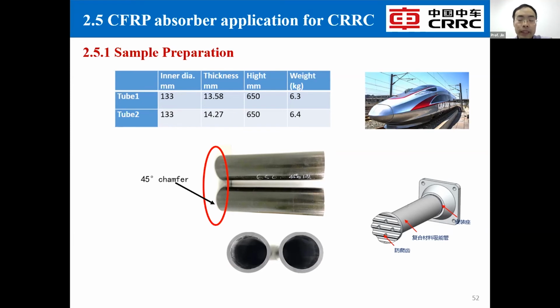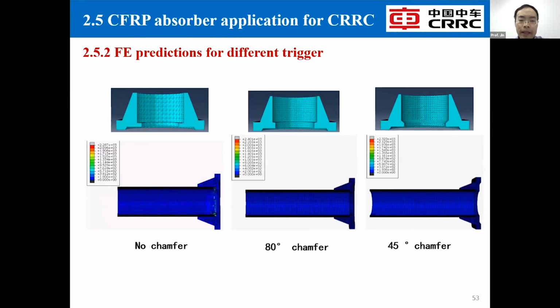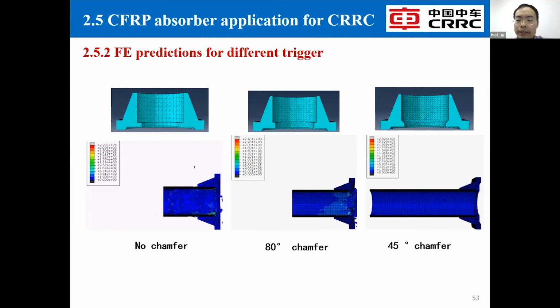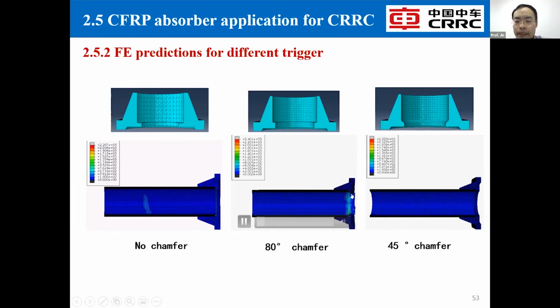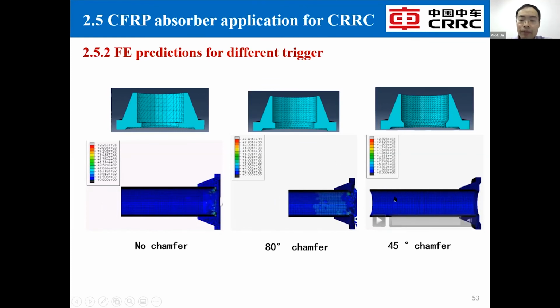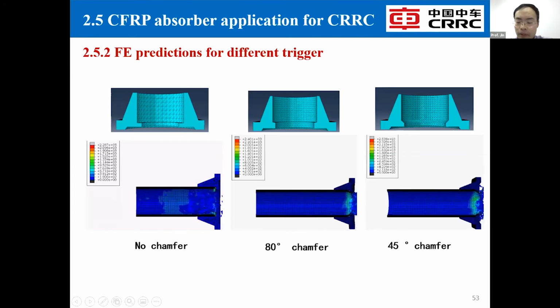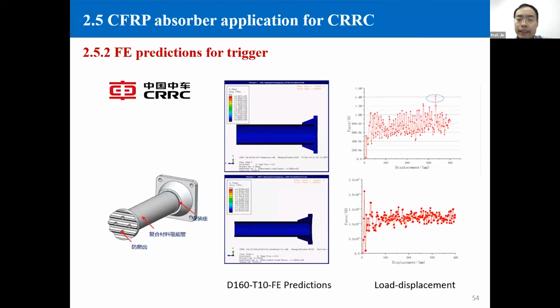And now we focus on the application for the high-speed train. The high-speed train requires a structure up to 106 millimeters in diameter, and requires a minimal peak load up to 600 kilonewtons. So we made these composite tubes, and we also used modeling to simulate the trigger. The simulation in the right-hand figure: the first case is without a chamfer, and the second and third are the composite tube and the baseline with different chamfers. And we found the composite tube with chamfer has a lower energy absorption capacity. And this is the simulation. Using finite element modeling, we are able to predict the peak load and the energy absorption of those structures.